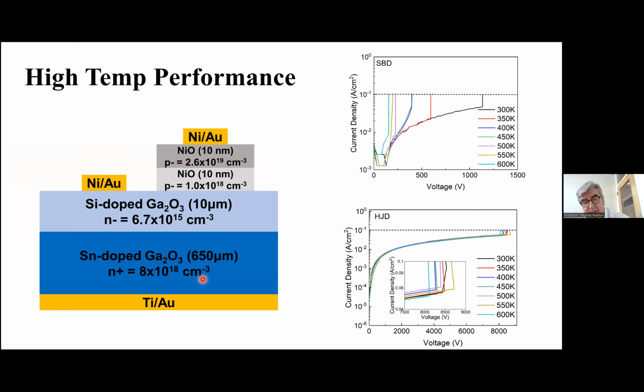So if you take a structure like this, a vertical rectifier, so this would be a Schottky rectifier. This one would be a p-n junction because you're using the p-type nickel oxide as the p side of the junction. Use a bilayer to get a low sheet resistance with good current spreading. Use a lower doping here to get higher breakdown voltage. And if you compare the temperature performance of this p-n junction rectifier with the Schottky rectifier, the Schottky rectifier only has a breakdown of around 1 kilovolt or so. And as you go to higher temperatures, the breakdown voltage has a very large negative temperature coefficient. So contrast that with the heterojunction diode, this guy, and what you're getting is a much larger breakdown voltage and hardly any decrease with temperature. So this is a very robust device for high temperature applications.